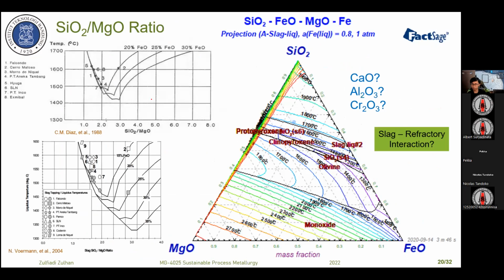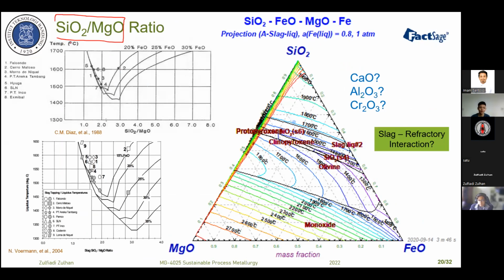Next, we continue to the silica to magnesia ratio in the slag. We see from this data, this diagram was published in 1988 by Diaz. And this is the new data we found in the literature in 2004, published by Voermann. We see that there is a relationship between the liquidus temperature of the slag, or melting point of the slag, and the silica to magnesia ratio and the iron oxide in the slag.